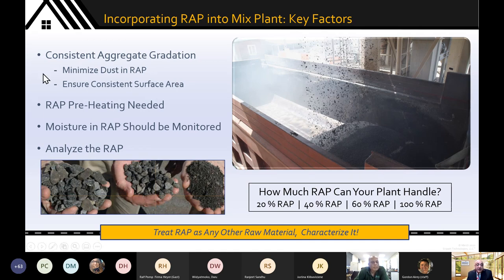Universally, I'll spend a moment on this. RAP preheating is generally required. Why do I say that? Well, if you're using 10, 15, 20% RAP, then maybe it doesn't act as that much of a heat sink. But if you're starting to put in 30, 40, 50, 60% RAP, now it is a sizable chunk of your incoming batch. And therefore, in order to minimize residence time in a drum, minimize residence time in a pug mill, you need to be able to preheat the RAP.